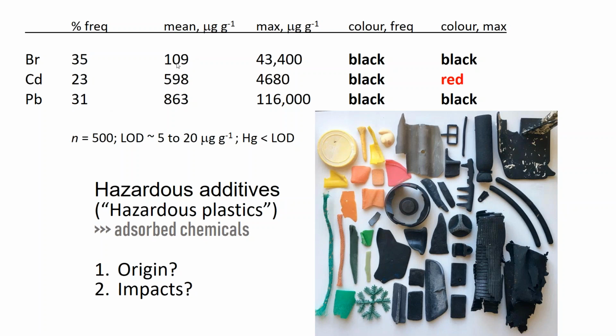These are the values that we find on average, several hundred microgram per gram, and we see the maximum values, 43,000 for bromine, 5,000 cadmium, 116,000 for lead. So just to give you a sense of scale, this is about 12% of the entire mass of this plastic sample was made of lead. So you can imagine it's quite dense, but it's also quite alarming perhaps that there is this much of a very harmful compound in beached material.